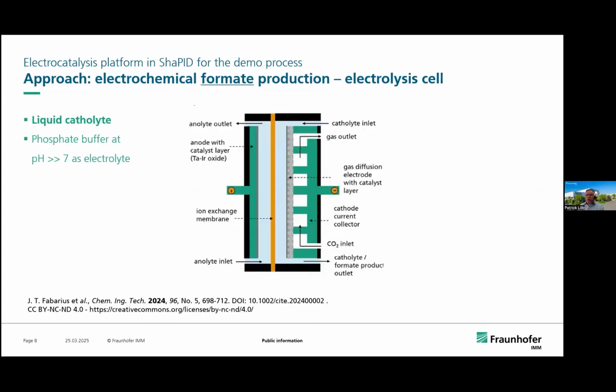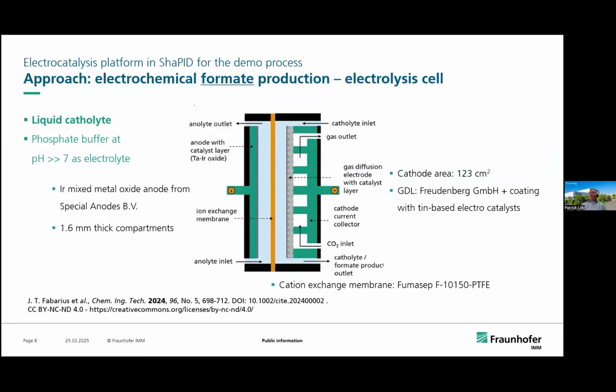In the project, we have looked at two cell configurations. One is using, as commonly used, a liquid electrolyte in combination with a phosphate buffer. You see here the cell configuration, and to give some more details on the cell we used for our investigation: we have an anode with an iridium mixed metal oxide from a commercial supplier, then 1.6 millimeter thick compartments with a cathode area of 120 square centimeters, and a gas diffusion layer from Freudenberg, coated internally by Fraunhofer IGB with a tin-based electrocatalyst, and we have a cation exchange membrane.